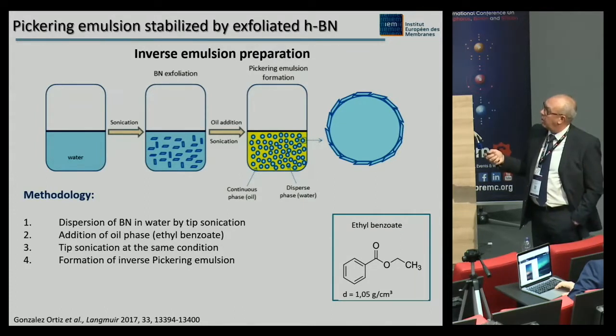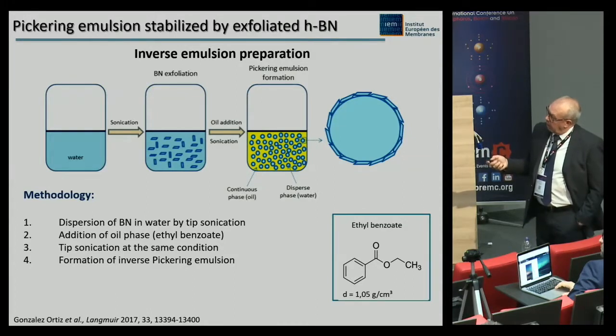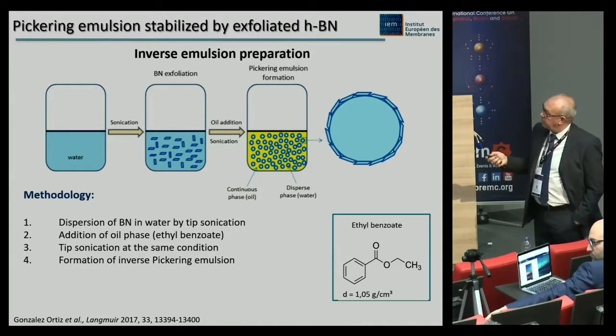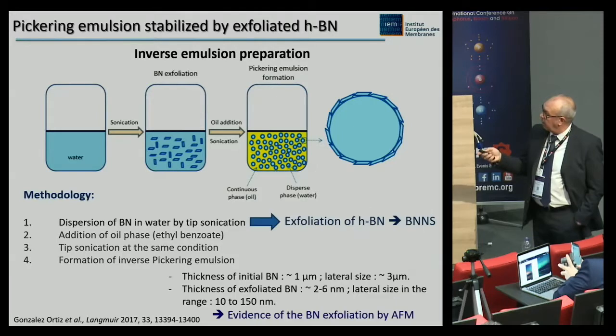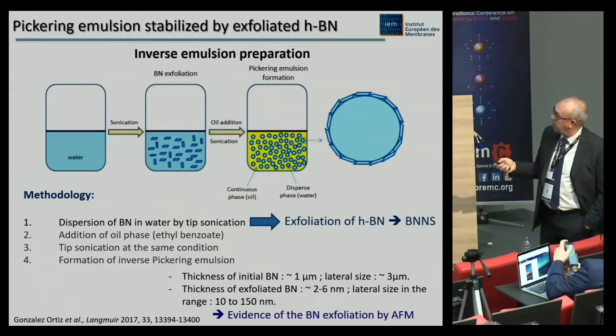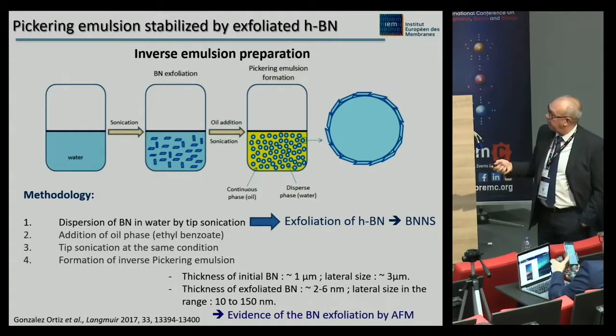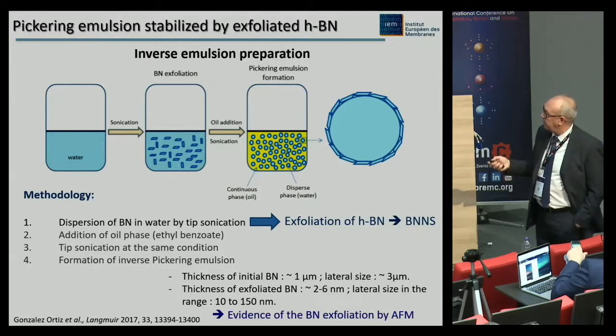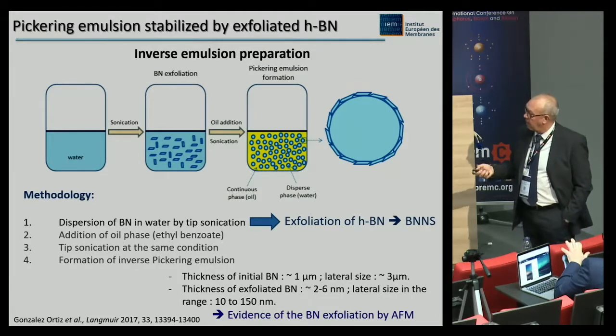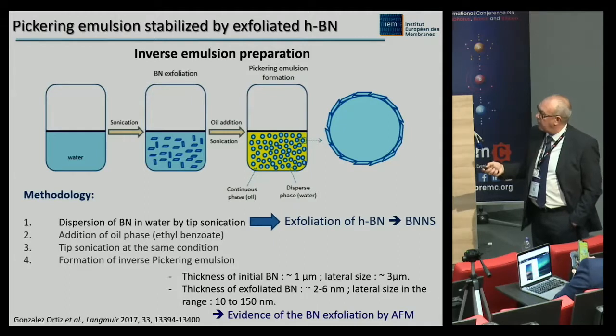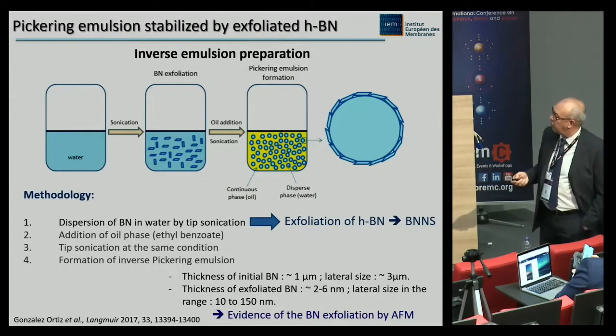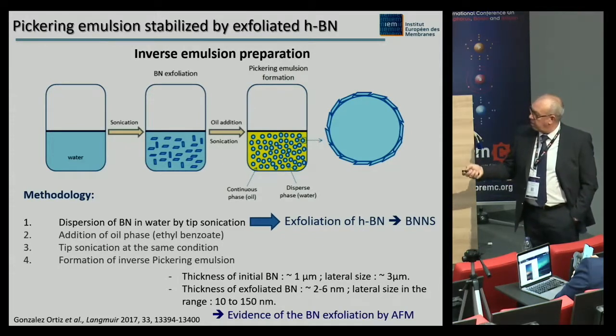You add oil to this system, and after that you sonicate another time, and you obtain this kind of dispersion in which the dispersed phase is the water inside the droplets, and the continuous phase is the oil. In our case, the oil phase is ethyl benzoate, and the exfoliation of hBN led to very small particles with 2 to 6 nanometers in width and a lateral size in the range of 10 to 150 nanometers, which is evidence of very good BN exfoliation, as shown by AFM. This has been published in Langmuir very recently.